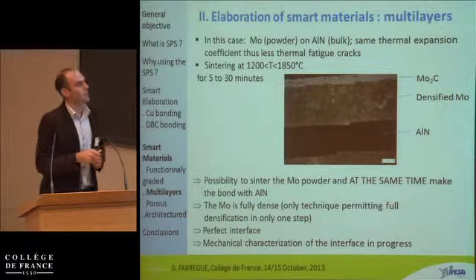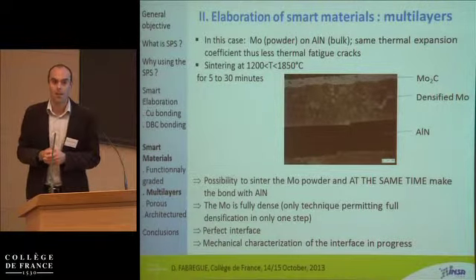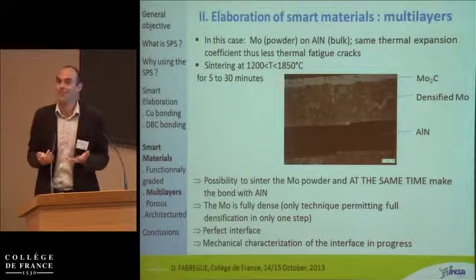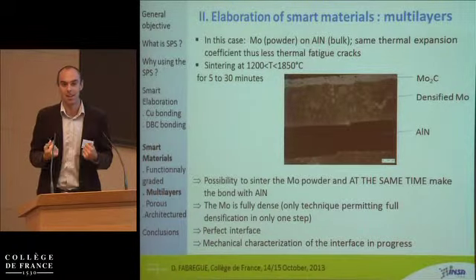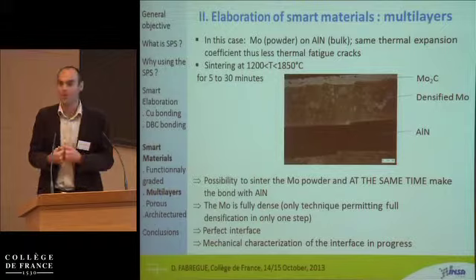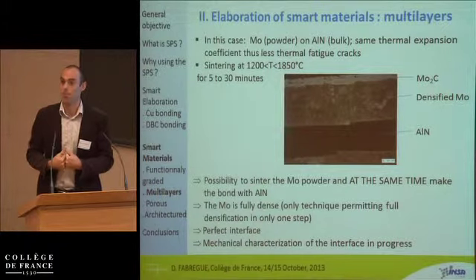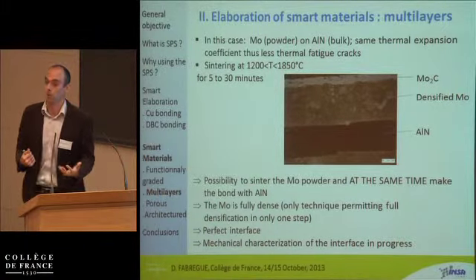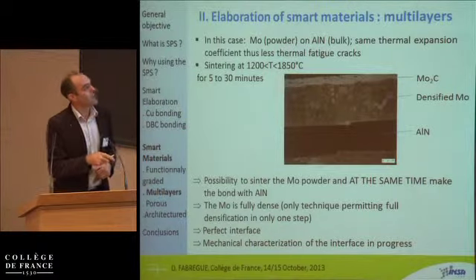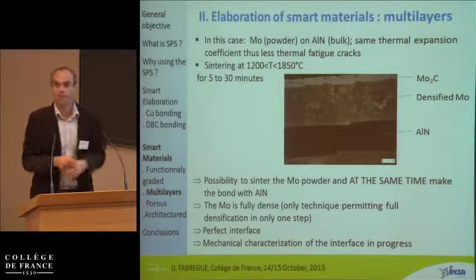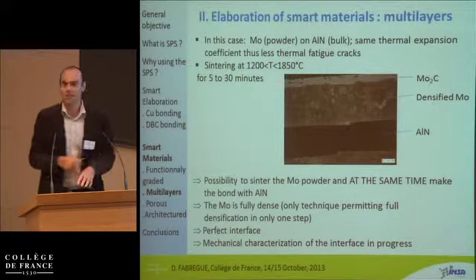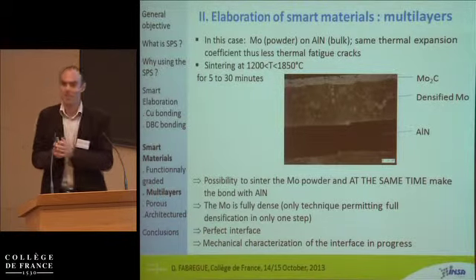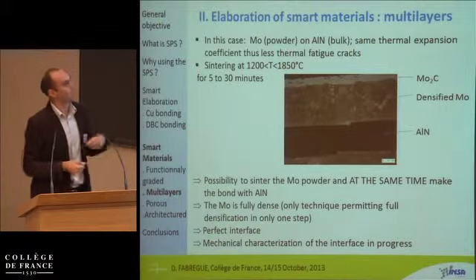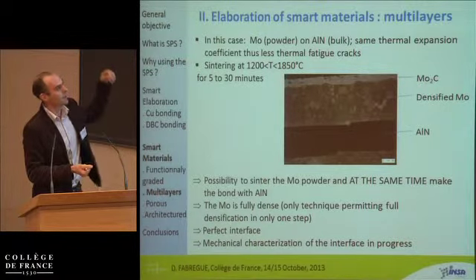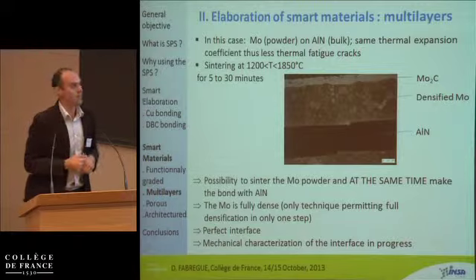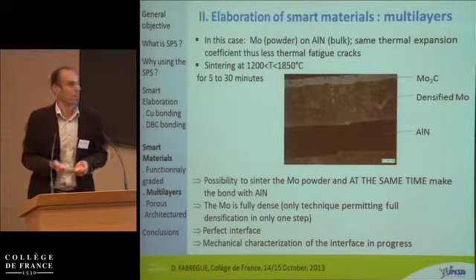Now, if we look at the densification of molybdenum, we found that we can have a fully dense molybdenum, which is the only technique that can provide densification of molybdenum in only one step. Usually you have a high deformation step afterwards. So you have a very well densified molybdenum and you have a good interface. I put perfect, I don't think it's perfect, but still, we did some mechanical testing, trying to shear these things, and this is pretty good in terms of mechanical properties.